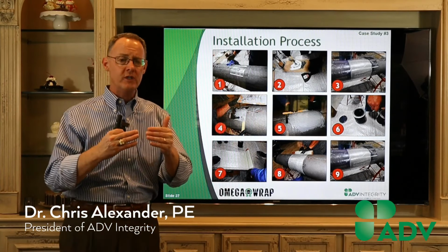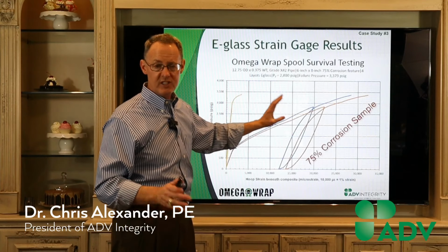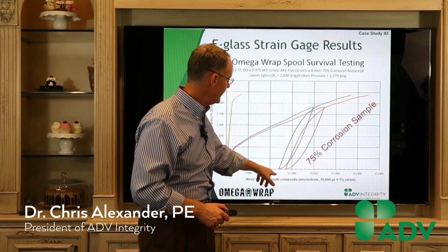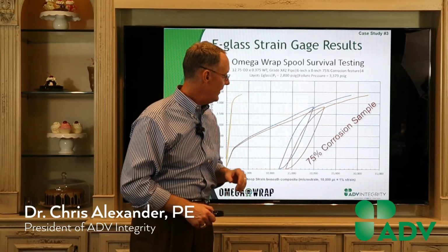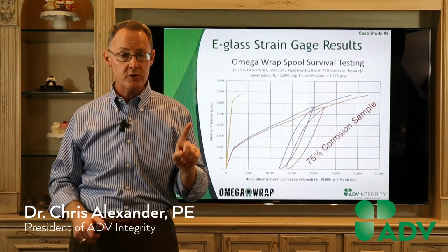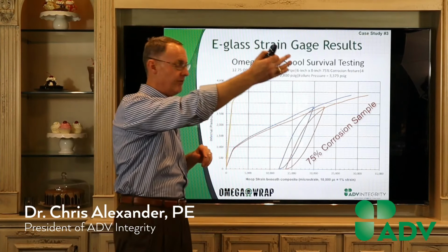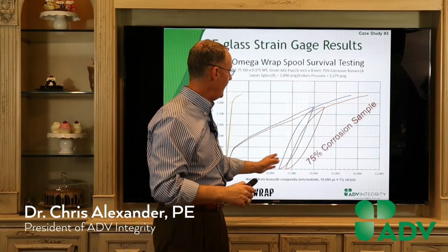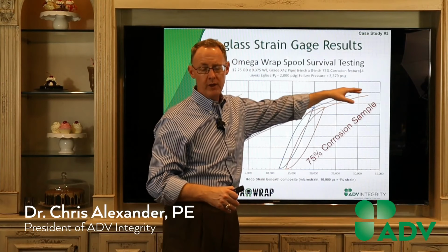So I alluded to earlier, we put some strain gauges on, so we go all the way up to the target pressure. We drop the pressure all the way down, and the fact that these curves don't go all the way back down to zero means that we introduced plasticity in that simulated corrosion region. And so you got 10 to 15,000 microstrain. 10,000 microstrain is 1%. So what that means is we plastically deformed it, we come all the way down, and then we go back up, and then we go all the way to burst.